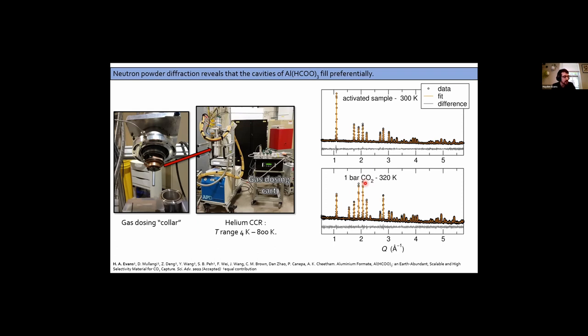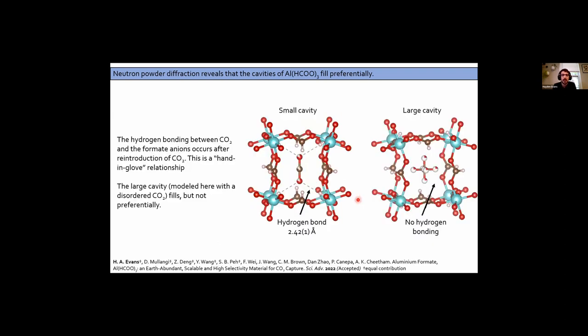As you dose the CO2 in, you get a change in the pattern, you can do your Rietveld refinement, and you can comment on what's going on structurally. And so what happens is that CO2 slips into the structure and it has this hand-in-glove relationship with these small cavity formate hydrogens, right? So you can see this hydrogen bonding length of about 2.42 angstroms. It's such a tight, beautiful fit that was destined to go in here.